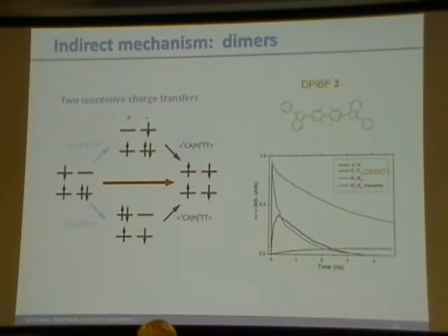And so it's not necessarily clear immediately. If the yields were above 100%, we would say, okay, this is great, singlet fission is occurring, and we know that it is. But with the yields less than 20%, it's a little more difficult to prove that it's happening. But one of the possibilities in these weakly coupled dimers is that we are undergoing singlet fission, but through two successive charge transfers. So this indirect mechanism, we form a real cation anion intermediate state. And I showed some evidence of that before, and I'll just show it again.